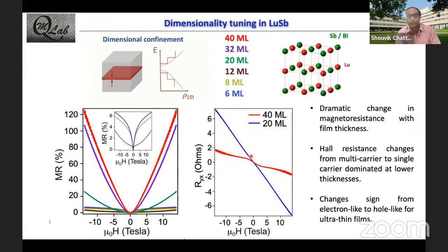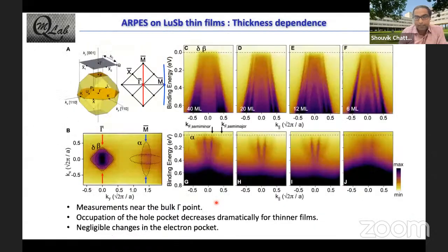So the natural question is, okay, can we understand this transport behavior? So we again take help of our ability to directly visualize the electronic structure in this material system, and we can do it also for very thin films. And what I'm showing you here are the same cuts as I'd shown earlier for different film thicknesses. As you can see here, your Fermi wave vector is going down as you go from the 40 to the 6 monolayer limit, but the electron-like pocket does not suffer that much of a change.